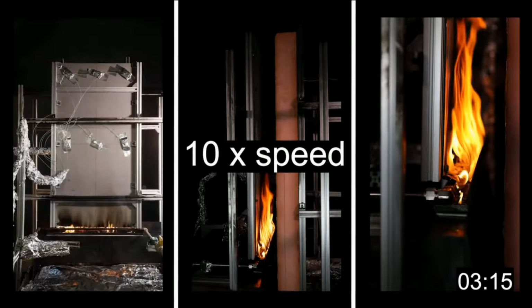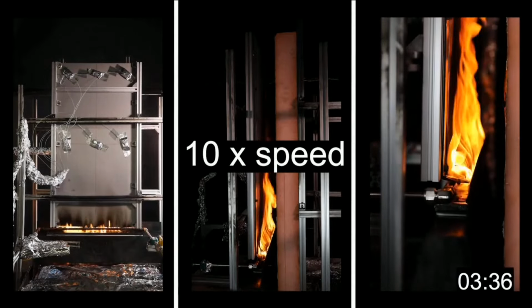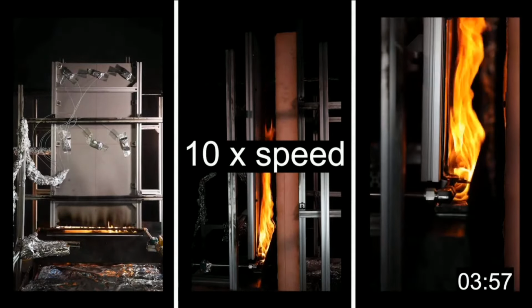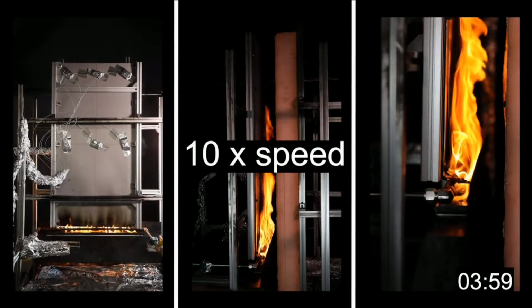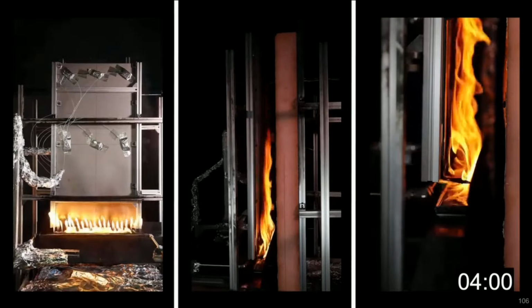So just there, the plate dropped off. Up to about 4 minutes, a pool fire of burning polyethylene continues to grow within the drip tray. The flames extend to about 3/4 of the cavity height by about 4 minutes. And remember, this entire rig is about 1 meter high, that sheet of ACM PE. At 4 minutes, the line burner is removed.